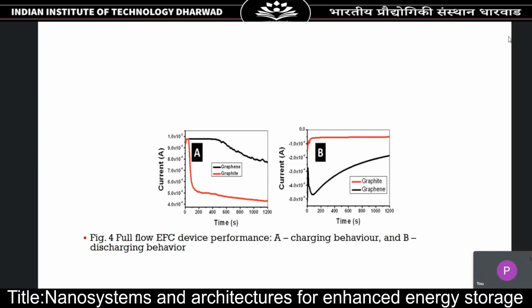And this is the full flow device. So we had two kinds of devices: one is intermittent flow and another one is full flow. We can adjust the peristaltic pump to control the volume of flow into the flow cell. If you take a charging behavior of a full flow device, you can see that graphene is performing much better than graphite. Graphite is shown by the red line. And similarly, the discharging behavior is better for graphene as compared to graphite.